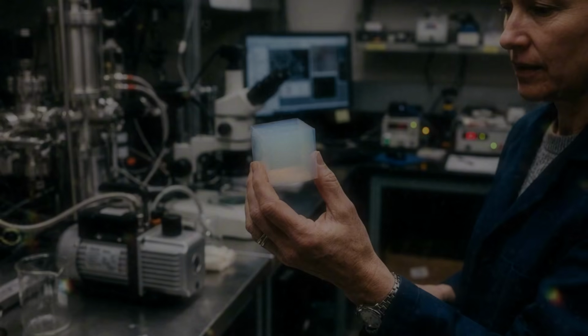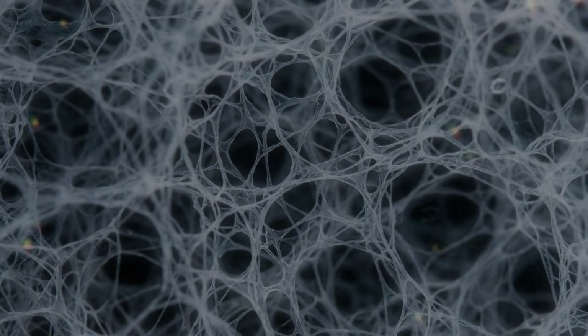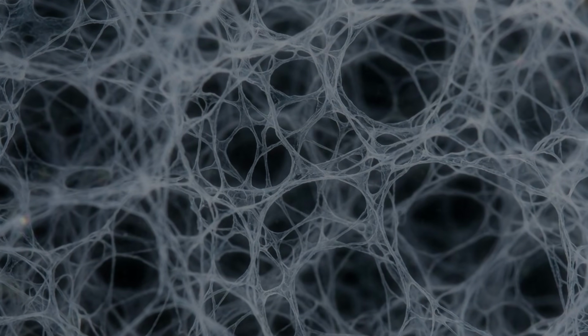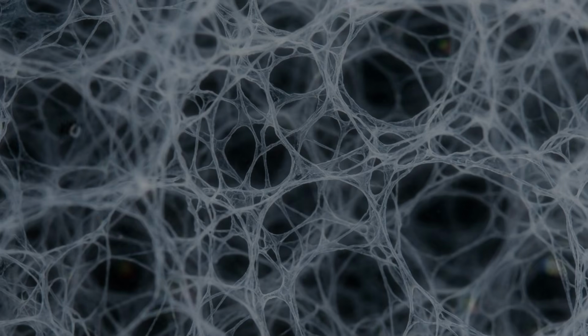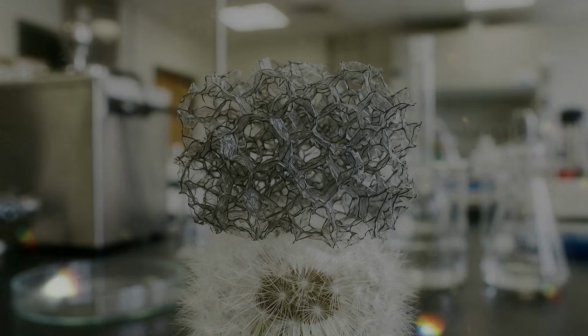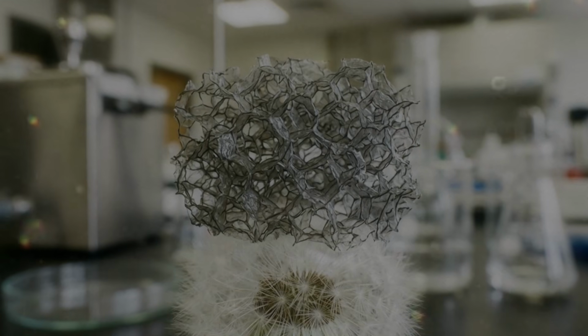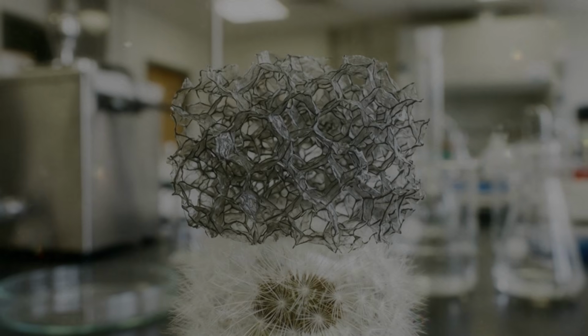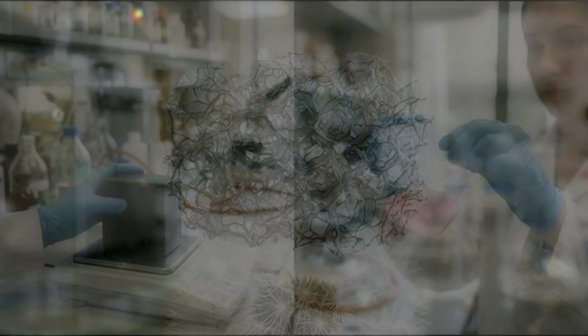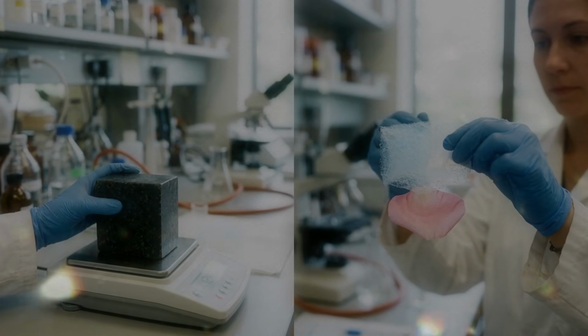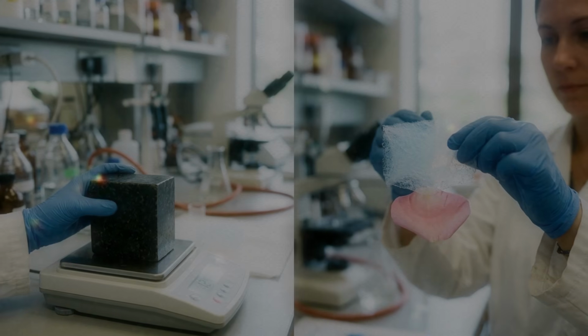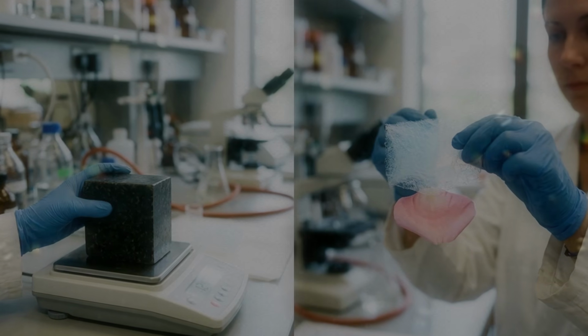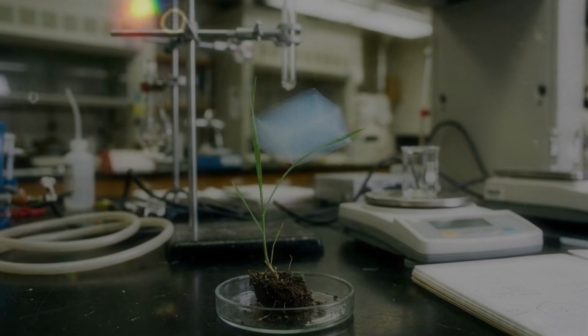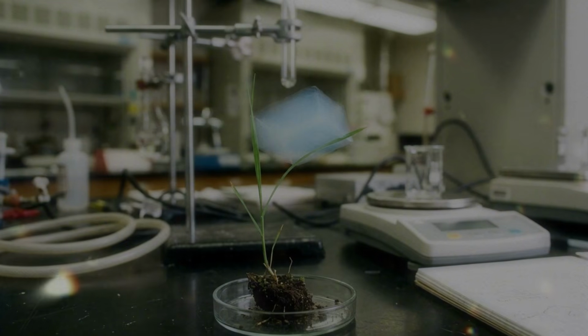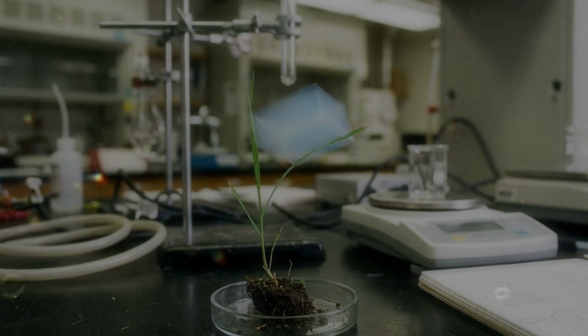Some aerogels allow a portion of thermal radiation to pass through. Others contain particles or additives that absorb or scatter it. An insulation material designed for high temperatures may include substances that reduce this radiative transfer. Without them, a very light aerogel can perform well at moderate temperatures but become less effective as radiation begins carrying more of the heat. The best thermal performance therefore comes from controlling several routes at once.